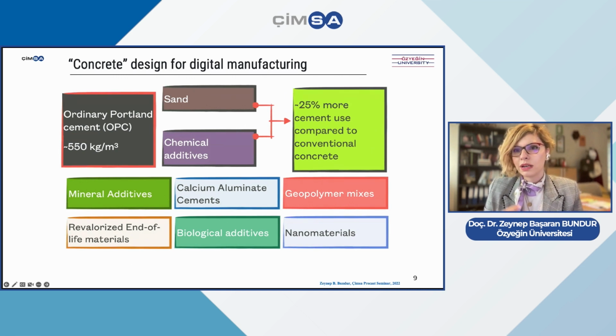The most important issue here is the ratio of sand. It's at the moment 1 to 1.5. What is reported is up to a maximum of 2 to 3 millimeters of sand, which is actually too small. We need to have the same volume of micro concrete or micro mortar that needs to be produced. I wrote here 25%, but that's too optimistic in that sense. We need to use 2 to 3 times more cement there.